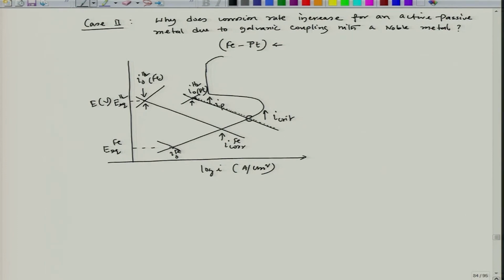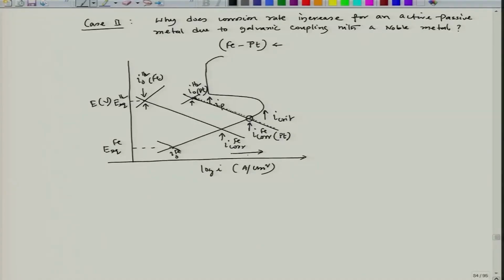So now this becomes my I corrosion of iron on platinum, when that iron piece is galvanically coupled with platinum. Now if you see, even in spite of the active-passive possibility of that iron, because of the position of E equilibrium of hydrogen evolution reaction and the I0 of hydrogen evolution on platinum and iron surface, the cathodic polarization line cuts the iron activation line in the active zone. So that is what hikes or increases the corrosion rate.